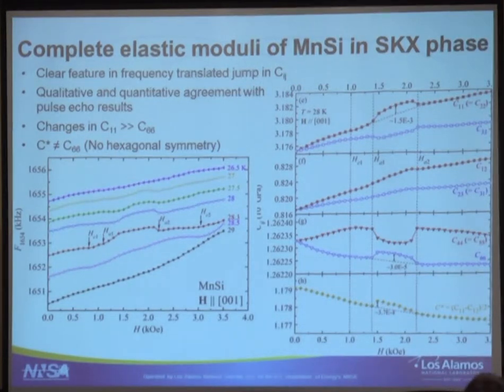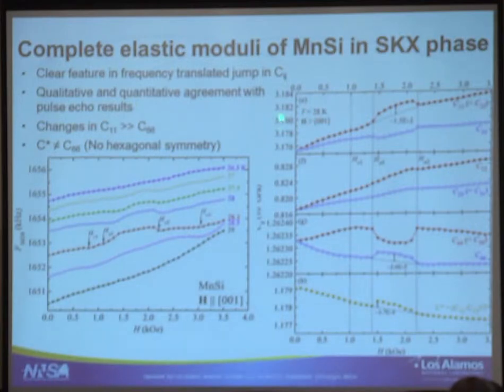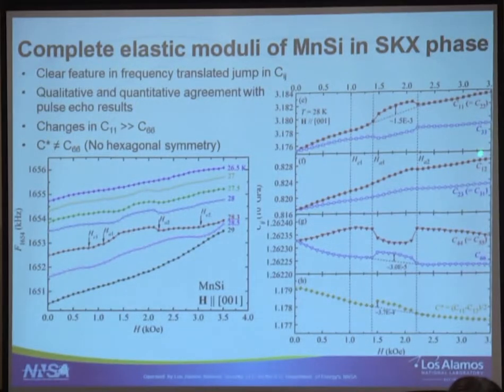So here are some of the results. So this is C11 and C33, C12 and C23, and also the C44, the shear mode C44, and C66. So immediately you can see that both in the pure compression and the pure shear, you can see the Skyrmion phase. The other thing you can see is that the values of the stiffening, let's say in C11, are much larger than the stiffening in C66.